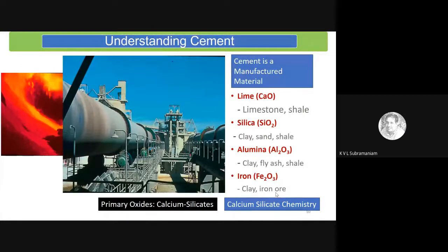This is similar to what was used in the lime mortar for 2000 years. And silica, we use sources like clay, which basically brings in the silica. So these are the raw materials which basically bring in the calcium and the silica that are needed to make the cement, so that we can produce a calcium silicate material.